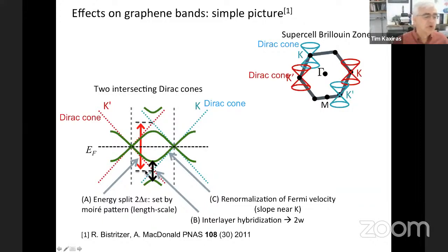This introduces now two energy scales. There's an energy scale here which has to do with the splitting in energy of where the Dirac cones intersect, and this is entirely determined, it's set by the Moiré pattern. The length scale sets this energy scale. There's another energy scale which has to do with interlayer hybridization, and this is the interaction between the layers. And this interaction is what splits the degeneracies here to produce these bands. And because of the splitting, there's also a renormalization of the Fermi velocity near the K points. So this is the basic physics introduced in reciprocal space, in K space, by the twisted bilayers.